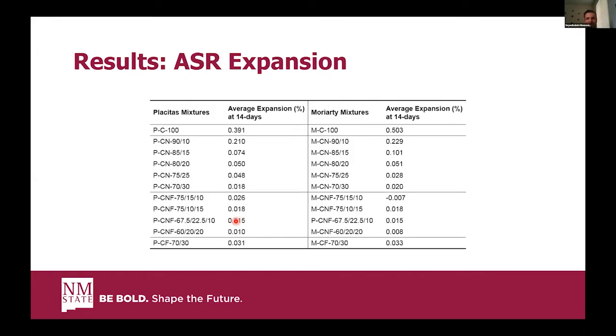In this slide, we can see that the expansion of mixtures with just 30% fly ash was much more than the mixtures with 30% natural pozzolan for both types of the aggregates. And it suggests that natural pozzolan can be a good alternative to fly ash in terms of ASR expansion.